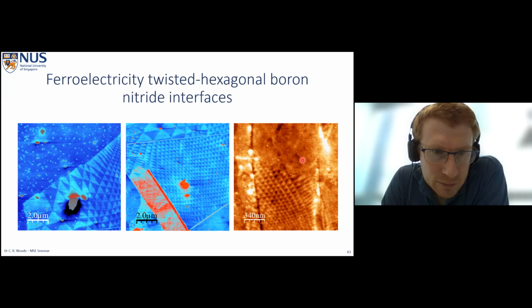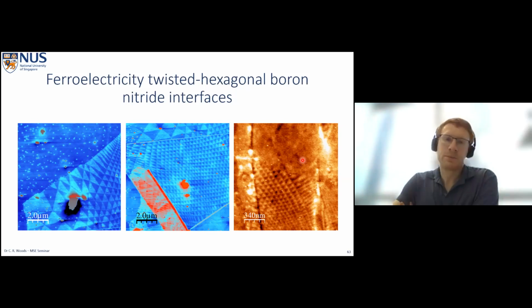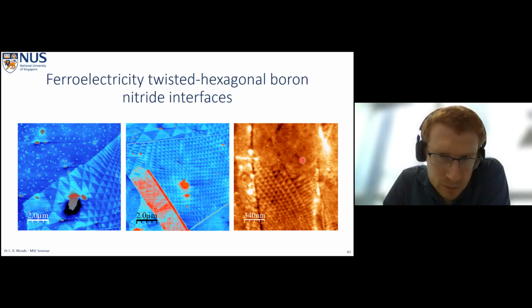And as you can see, and you probably can expect, it's not perfect, right? If you make a perfect twist, you would have a perfect periodicity. And here you see that this pattern is a bit inhomogeneous. That's obviously going to come from imperfections of the topography pretty much. So can you say how many units in your experiments you have a very, very homogeneous pattern? And at what length scale does it become inhomogeneous? And then maybe, what are the main features that are introducing these inhomogeneities into the moire pattern?